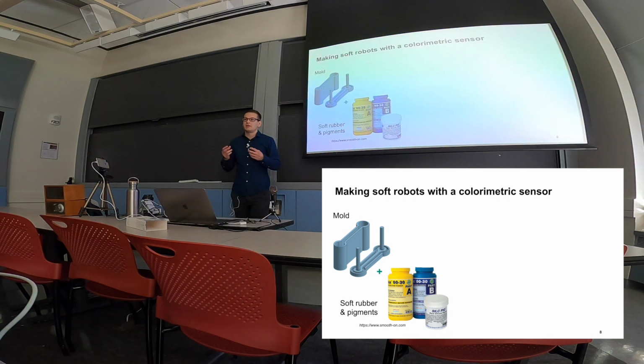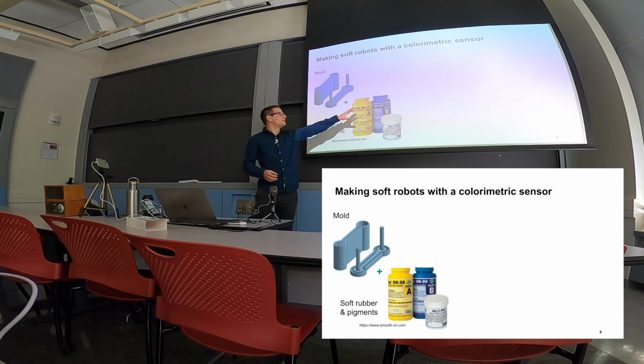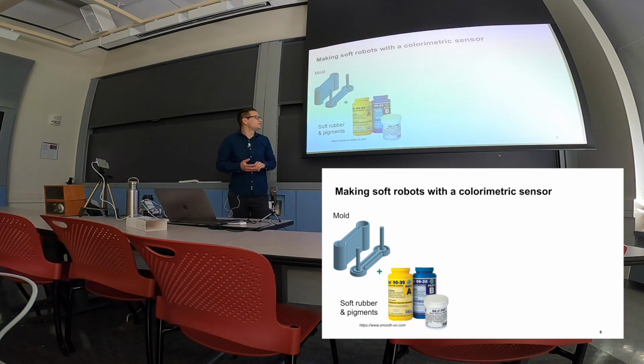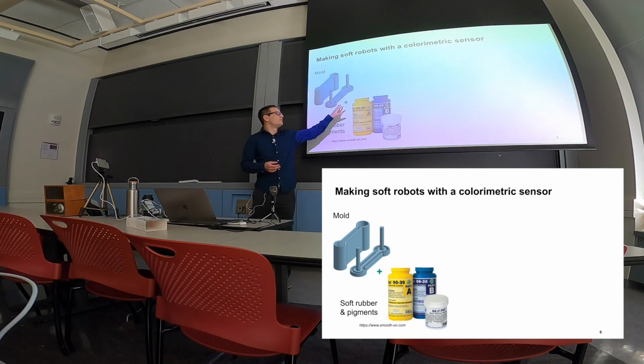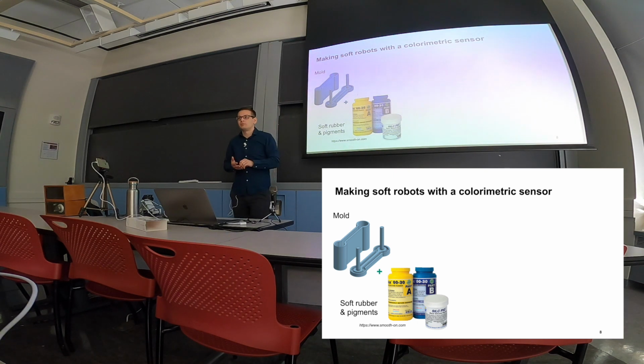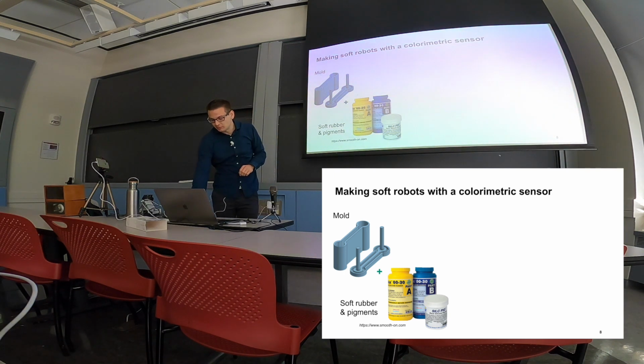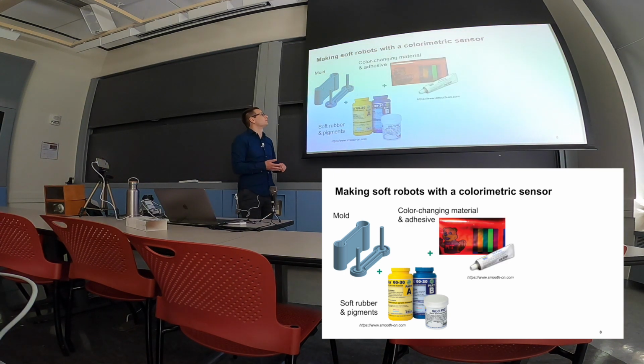To verify whether I could use this material in the field of soft robotics, of course, I needed to first learn how to build such soft robots. And during my time over here, especially in the first weeks, I got to know that for soft robots, one usually just creates a mold, which is the negative of the soft robot, and fills that up with the material out of which the soft robot should consist, so a soft rubber, which is in the first state usually liquid, and two components that we can then mix and cure inside of the mold. Then it will cure, and we can remove the ready soft robot out of the mold afterwards.